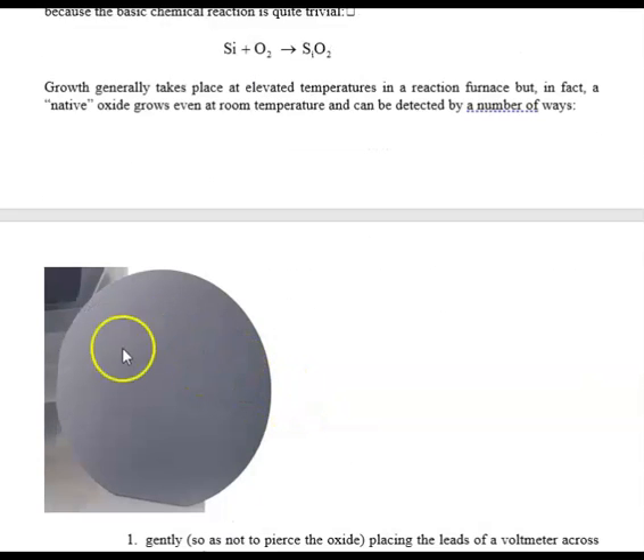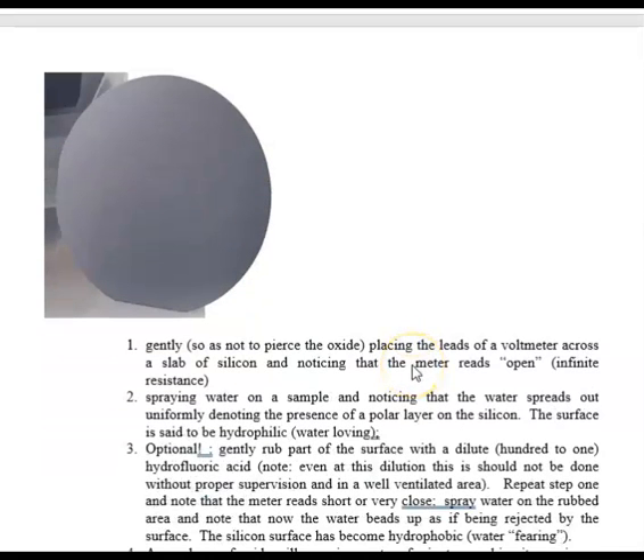And if we take a look at this bare silicon wafer, you say, well, that's at room temperature, I would expect there would be, well, silicon, and you would be, unfortunately, not right. This is silicon, that's true, but on its surface there is a very, very thin layer of oxide, and we can show that. We can show it by taking a voltmeter and placing the leads anywhere along the silicon, doesn't matter where, and if we do it gently enough, we don't want to scratch this gentle oxide that's on the surface, we'll find we get an open reading.